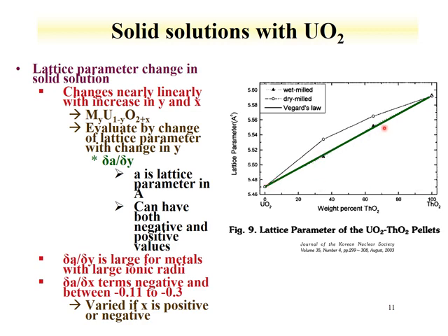And we would just see that this is the lattice parameter in angstroms for thorium dioxide, and this is the lattice parameter for uranium dioxide. A mixture is just a linear combination of the two. So for something that's 50%, the lattice parameter would be a contribution of 50% of the uranium dioxide and 50% of the thorium dioxide. If one takes a compound as a solid solution and measures the lattice parameter with X-ray diffraction, you can determine the composition of both. So this linear change is Vegard's law.